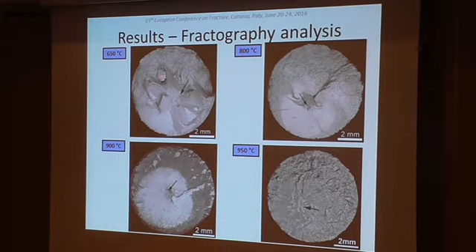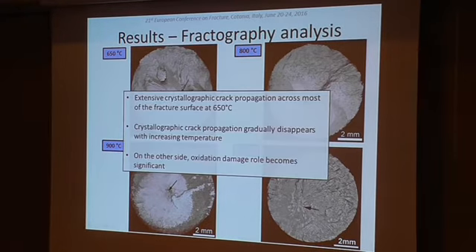At temperature 800 centigrades, it's already just in some areas in vicinity of initiation sites, and from temperature 900 centigrades and upper, we didn't observe this mode anymore, and oxidation was gaining importance in damage mechanisms. So as I said, we had at temperature 650 extensive crystallographic crack propagation across almost most of the fracture surface, and with increasing temperature, this mode was disappearing.